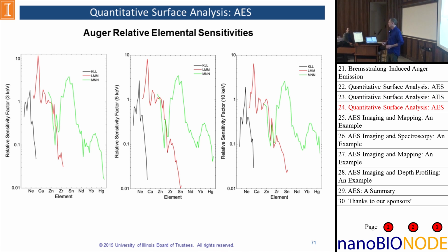And its sensitivities span the same range, 3 orders of magnitude, as XPS. So the one thing you'll notice on this log scale is that they'll hit a peak, and then the sensitivity will sharply drop. That's because the Auger transition is a many-body process. You have to get 3 things to work out right for the transition to work. And so usually that only works for a small range of elements, and then you lose signal.